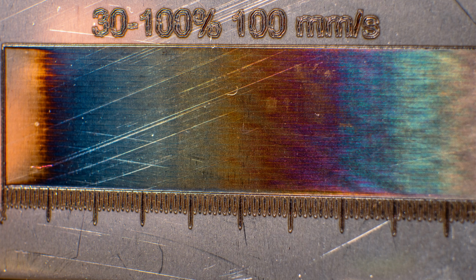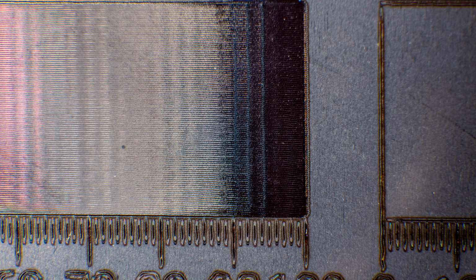I managed to get the laser up to 100mm a second, and then I was still getting the full colour range, going from 30% power to 100% power. But if I'm doing a design that needs some really dark black in the gradient, then I need to run it as slow as 30mm a second still.